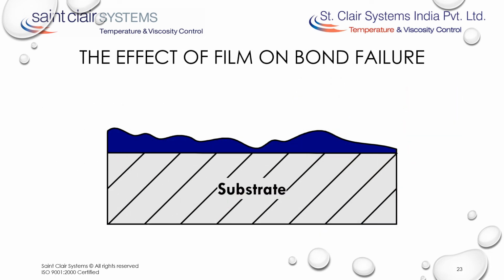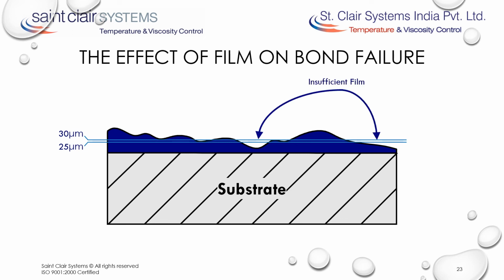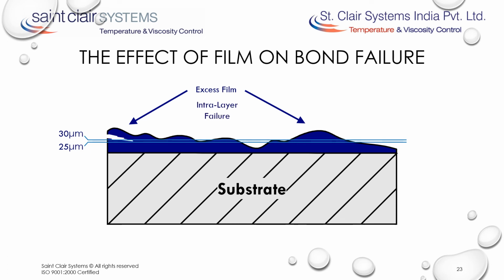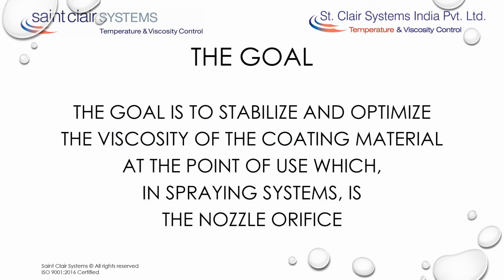So now, let's return to our film build example. Here, we can see that we have film thicknesses both above and below the recommended 25 to 30 micron range. Accentuated by the unevenness of the surface, the areas with insufficient film will be more difficult to bond to and will be prone to interlayer failure. Conversely, the areas with excess film will be subject to intralayer failure because the excess thickness compromises the strength of the layer. In order to get a predictable film repeatedly, the goal must be to stabilize and optimize the viscosity of the coating material at the point of use, which, in spraying systems, is the nozzle orifice. No other material temperature in the system matters to the stability of the coating process. So how do we manage that?